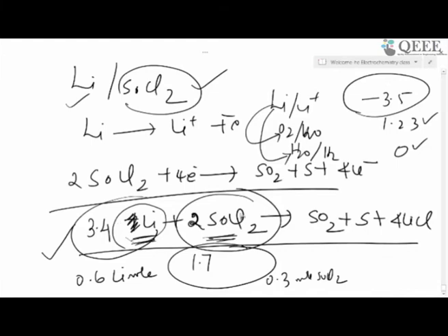So, I design a battery such that stoichiometrically I keep less lithium than thionyl chloride, so that after complete discharge of the battery, you may not have any lithium in the 0 state. All the lithium would have gone to the +1 state, which is harmless, so that even if the battery is disposed of, it won't cause any ill effect to the person who is handling that.